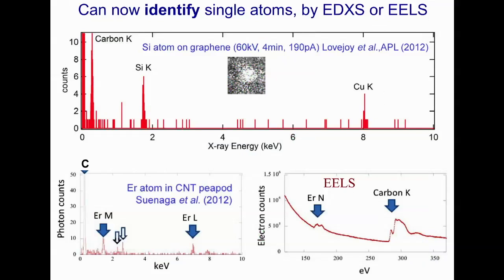As a result of these technical improvements, it's even possible to identify a single atom of many elements, using either EELS or EDX spectroscopy. The X-ray spectrum at the top was obtained by placing a 1.4 angstrom diameter STEM probe on a silicon atom for about 4 minutes. The sample was single-layer graphene, with silicon atoms occasionally substituting for carbon in the 2-dimensional lattice. You can see carbon and copper signals from the surrounding environment, but also a clear peak at about 1.8 keV that is characteristic of silicon.